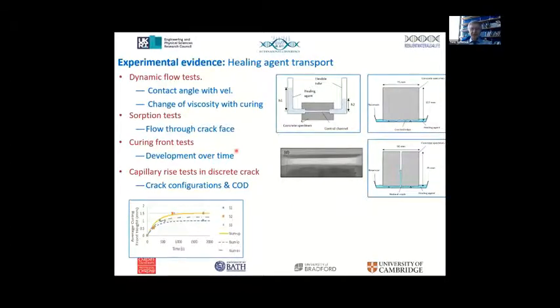Curing front tests have been important to us to understand how curing takes place next to a cementitious substrate, either concrete, mortar, whatever. Without that experimental evidence, we would have gone down a very different line in creating a model that has crack opening and crack rate dependency, and how the capillary moves as it goes up a crack. This is a sorption test.